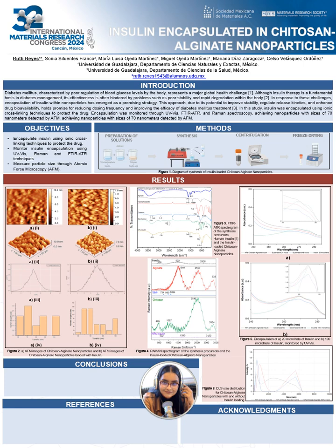Finally, I would like to talk about the DLS results. We have particles with a hydrodynamic radius of up to 1,000 nanometers, with other peaks at 100, 200, 400, and 800 nanometers. These large sizes detected by DLS can tell us a lot about the system's stability, indicating the need of a technique to reduce nanoparticle aggregation, which is common for polymeric particles. One possible approach could be the use of ultrasonication or the addition of polyethylene glycol in the synthesis.